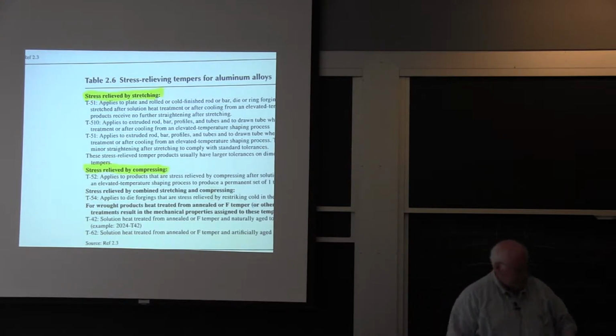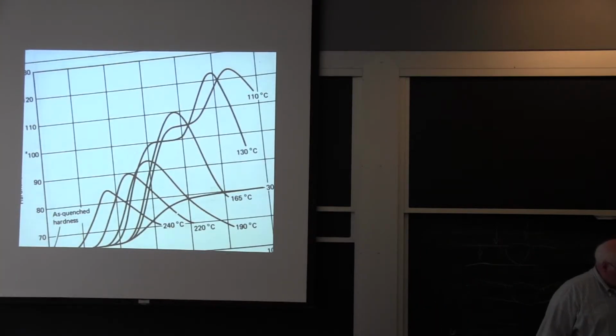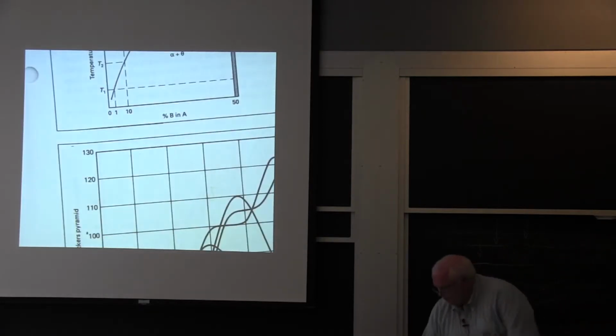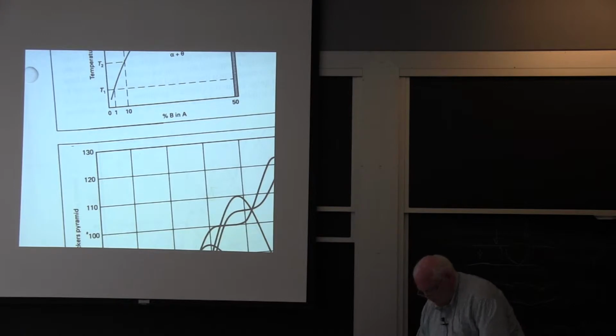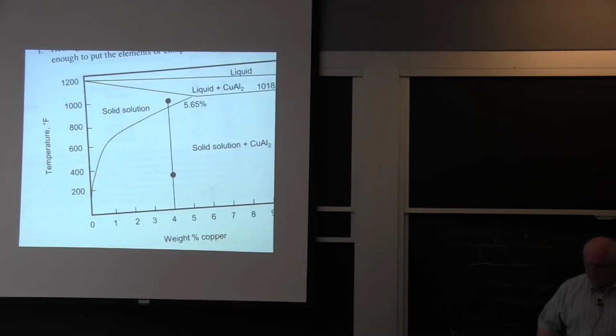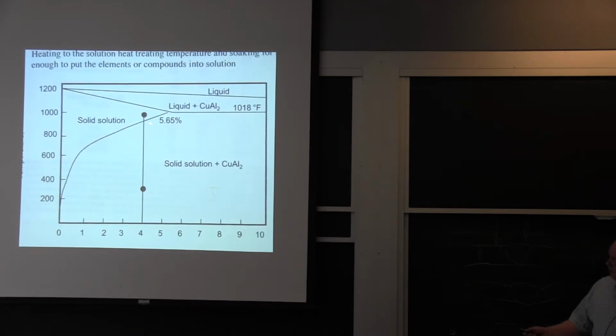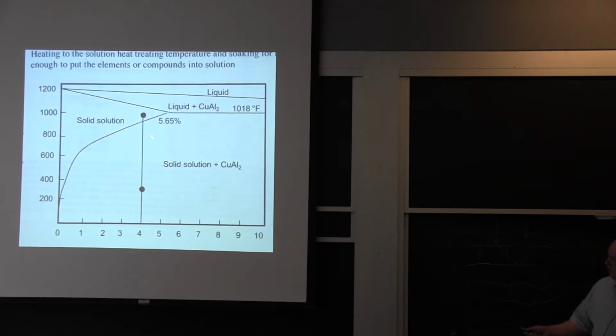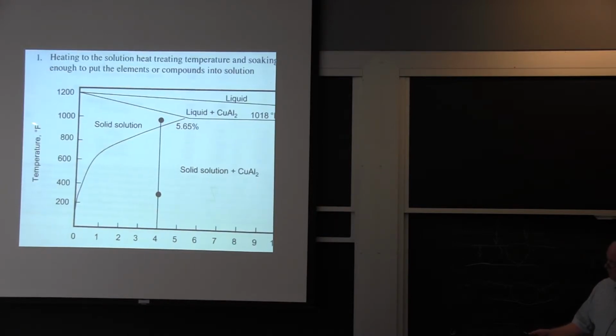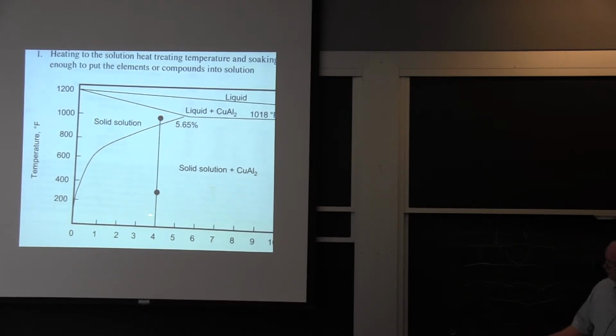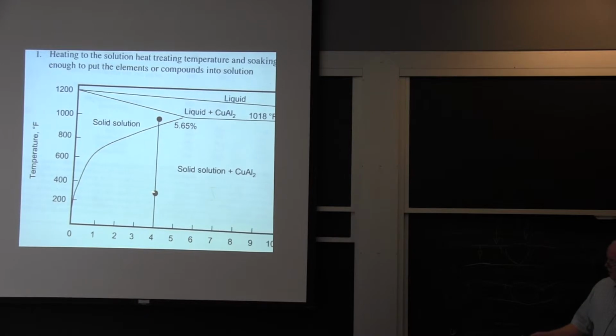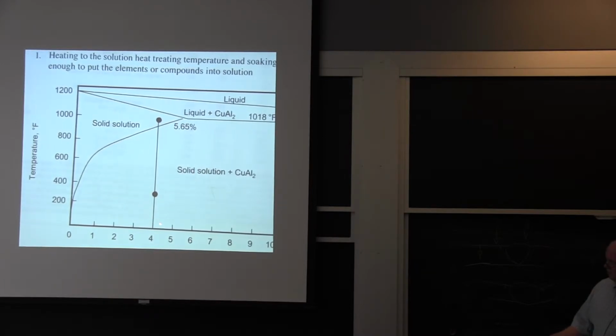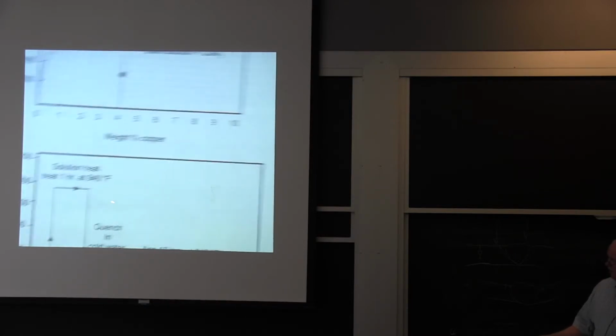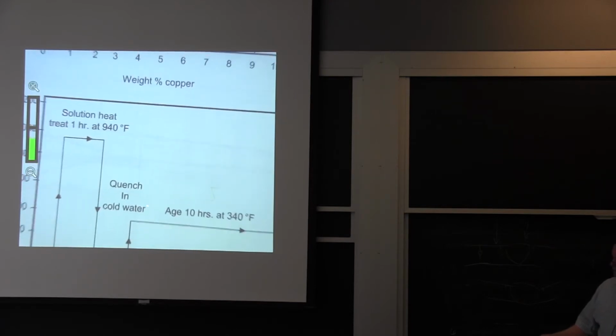If I do precipitation heat treatment on aluminum alloy, I might as well do everything here. It's kind of the next stuff anyway. To heat treat an aluminum alloy, this is an aluminum copper alloy here. I take it up into the solid solution range, which is around 1,000 degrees Fahrenheit. And then I quench it down to room temperature in water typically. And I can't do air hardening like I do with steels. I usually have to quench it in water. And then I bring it back up to a tempering temperature. And the schedule might look like this.